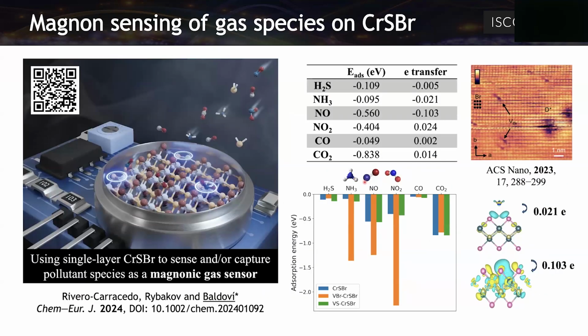We were also investigating now the potential of this material as a magnon sensor. Now, instead of using organic molecules, we were placing gas species, pollutants, and we were studying all these pollutants, for example, ammonia, NO2, CO, CO2. And in this case, we observed that the adsorption energy is much smaller than in the case of the organic molecules, and also the charge transfer. But we wanted to investigate also the effect of the vacancies in this material, because we know that it has been reported, in this work for example in ACS Nano last year, that it has vacancies of bromide and also vacancies of sulfur. So we wanted to test what the effect is for the adsorption of the gas molecule.